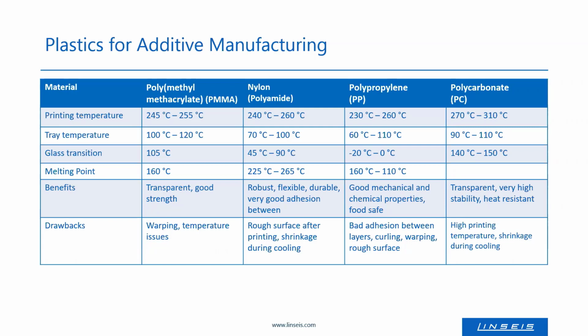The polypropylene, for example, is also used. It has similar printing temperatures to the other materials, as well as the polycarbonate. And here they have also some unique properties. For example, polypropylene has very good mechanical and chemical properties, so it's also resistant against some chemicals. The disadvantage here is that it's rather complicated to print, because the adhesion between the layers is not that good and the layers tend to curl. And the polypropylene is not really heat resistant. That is also a disadvantage.